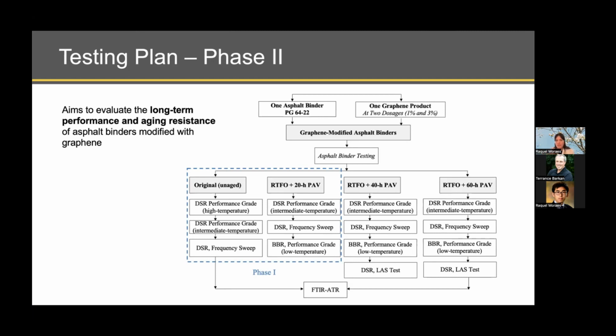So further evaluation is what is proposed as a following step for phase 2. If you remember from the last set of data that was presented, we saw that these additives decrease the aging susceptibility of the binder. However, we would like to really quantify if these additives could really decrease this aging susceptibility when they are subjected to very long-term aging. Because when we age the binder for a longer term than what is used in the Superpave standard protocol, we can clearly capture the effects of aging on the binder in terms of, for example, increased stiffness or increased hardening and brittleness for the binder.